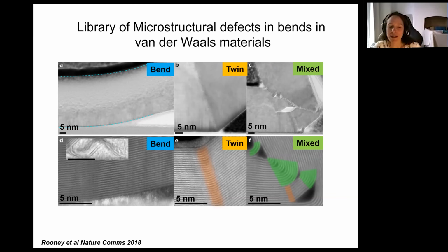It's also okay if you have a monolayer or maybe a bilayer specimen. So very thin crystals are very, very flexible, especially for graphite or hexagonal boron nitride. We know that the strains that graphene can accommodate are enormous. And so if you have a very thin crystal, that can flex and bend. If we have a slightly thicker crystal, we need to accommodate the strain associated with bending and preserve single crystal stacking because that's very favorable energetically. And to do that, we produce these twin boundaries.